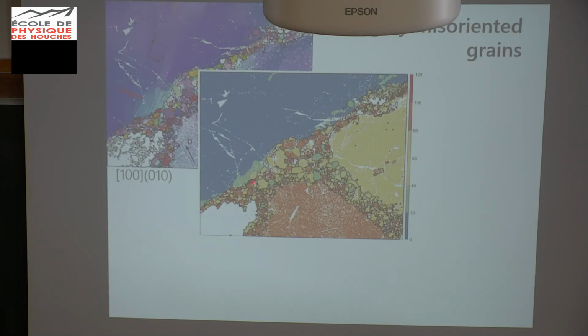But then we can see here a dynamic recrystallized grain in red. So there is a jump of 50 degrees in misorientation, and there are even more extreme cases here. These grains in orange that go from blue to orange, that is more than 80 degrees of misorientation. So maybe you can think, okay, but maybe this is not the parent grain, because the reference frame is the